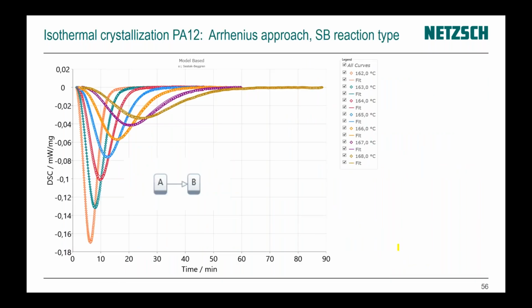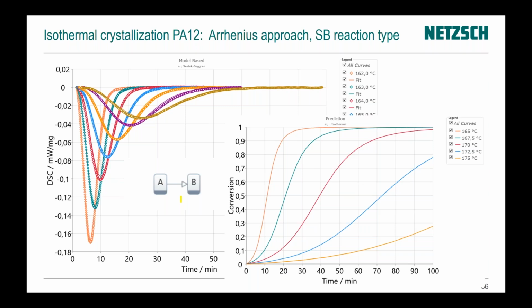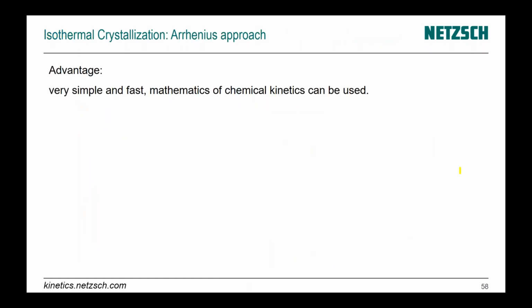Here we apply for polyamide the Arrhenius approach with Šesták–Berggren reaction type - very good fit - and we can use this model for simulation, for example, simulation of degree of crystallinity for other temperatures. But again, the Arrhenius approach works only for isothermal crystallization and only for isothermal predictions.